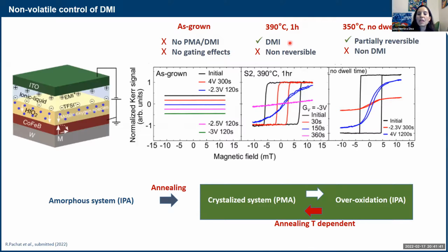It's something that we can understand when we think about what we do with the temperature. Actually what we do with annealing is crystallizing the structure. In an amorphous film, we have better chances of having ions moving back and forth without much of a problem. However, if we have a polycrystalline structure in grains that are crystallized, one can think that it's relatively hard to actually put ions through these crystalline areas, and especially to get them out. So the ionic mobility is really affected by this.